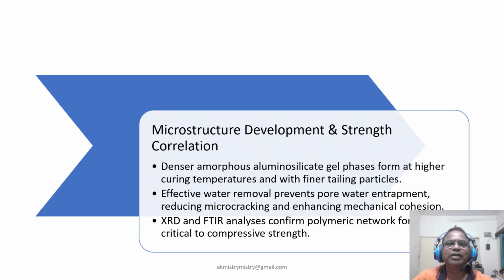Now, at the microscopic level, curing and mix design dictate how dense and cohesive the geopolymer gel becomes. When finer tailing particles and proper curing conditions are used, a denser amorphous aluminosilicate structure forms. One big factor is water removal. Trapped water creates micro voids and micro cracks that weaken the material. Effective drying ensures that pores are minimized and the geopolymer gel forms a very cohesive network. Techniques like X-ray diffraction and FTIR confirm the presence of these gel phases and directly connect them to improved compressive strength and durability.